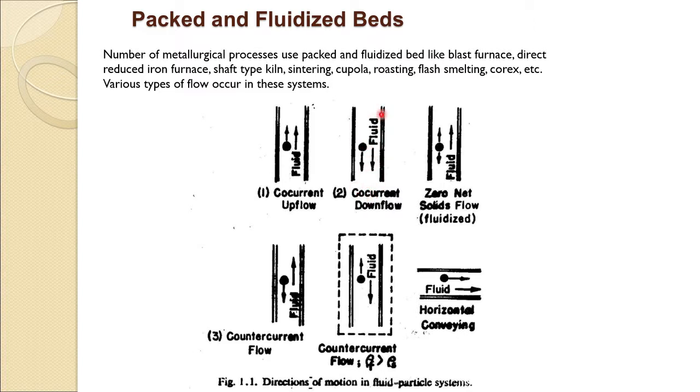And you remember this is the one situation which we discussed just now for the blast furnace, co-current indirect reduction process, in which we showed that that is quite inefficient and the consumption of coke is the maximum, about 1060 kg coke is needed per ton of iron. So that is one of the examples which we took also.